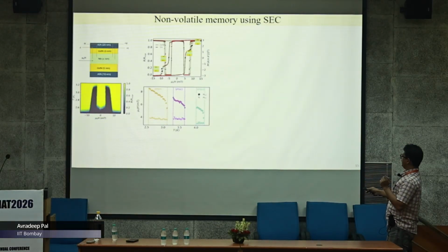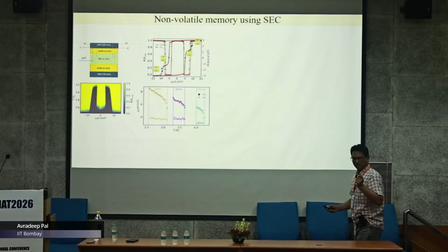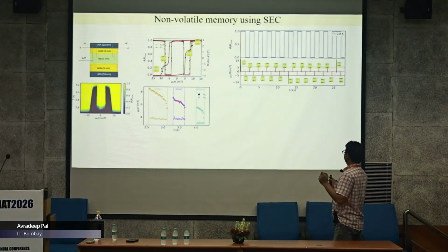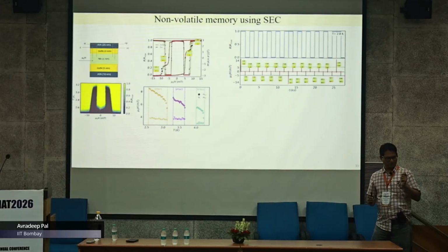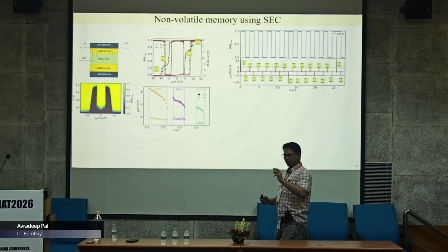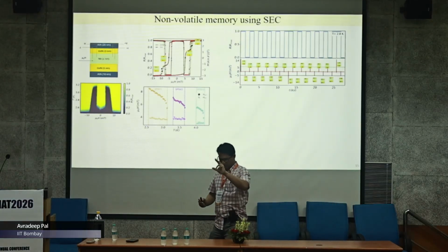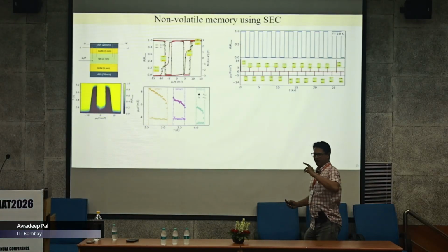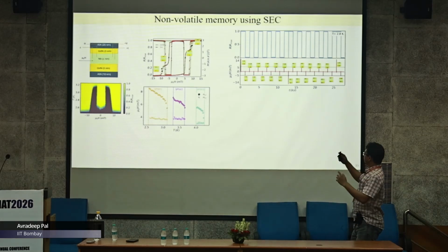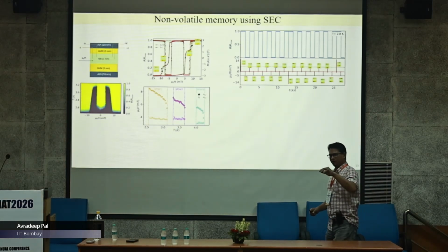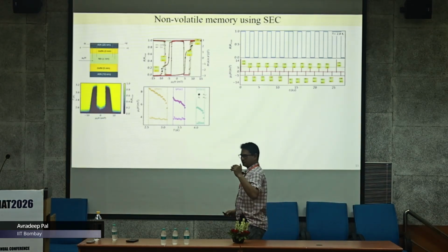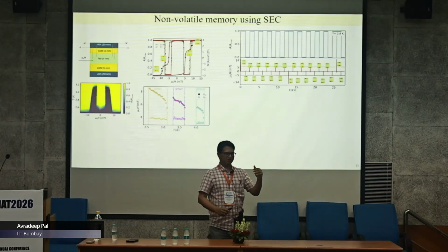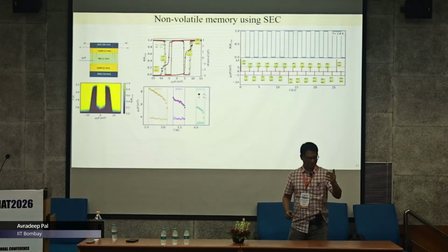However, when I reverse that same ferromagnet, when I come to this positive field and switch off, what should happen is that I should get a non-superconducting state at zero field, okay? So, you see, this is a very nice bistable switching device, okay? At zero magnetic field, I can change fields a little bit, toggle between these small fields and come to zero field, and I can measure a very nice, completely superconducting state or a completely resistive state.